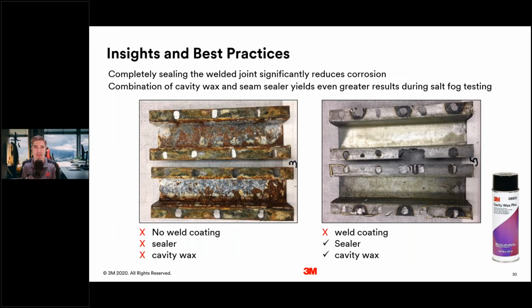And how we've highlighted that is here we've built 2 frame rails and did a combination of squeeze type resistance and MIG welding. And the frame rail on the left, as you can see, went through that 500-hour salt tank, and we had no coatings, no sealers, no cavity wax. And at the exact same time, the rail on the right went through the tank, and all that one had was just a radius off bead around the outer edge of the flange, and cavity wax on the inside. There's no weld through primer on there. That entire flange, you can possibly see that it's all ground down, 80 grit grinder marks on there.